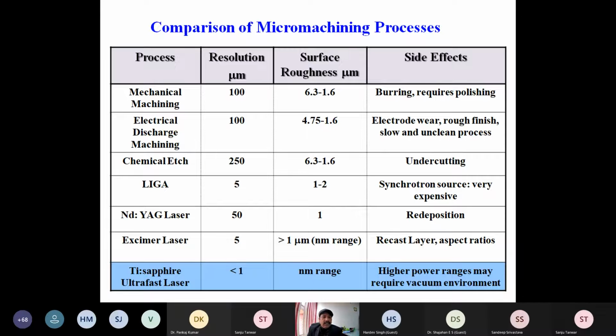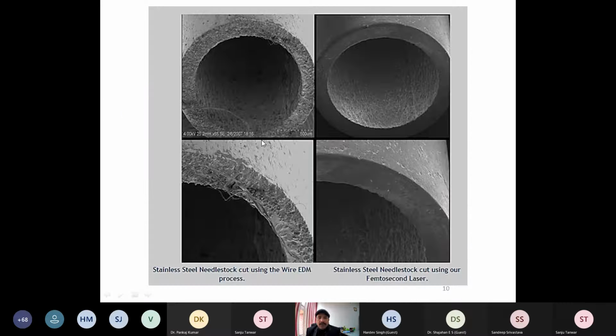If you compare with the laser-based techniques, like the Nd:YAG laser-based technique, the Excimer-based technique, or the Ti:sapphire-based technique, you see the distinction is very clear. The best resolution you can get is with the ultrafast laser, where the fine structure you can grow is less than a micrometer, and the surface fineness is also of the order of some nanometers. However, no technique is best, and as per the need we should use the appropriate technique.